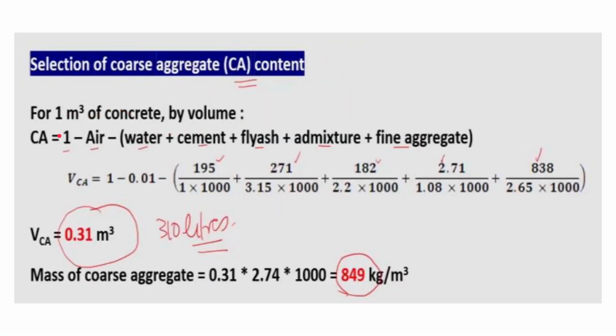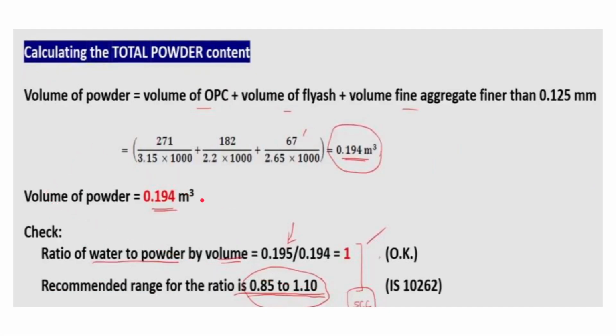Now by using the concept of specific gravity, volume and all, if we equate, we will find the volume of coarse aggregate as 0.31 meter cube. This is the normal calculation procedure, and we have to use this for finding the amount of coarse aggregate to be added. So the mass of coarse aggregate to be added is 0.31 times 2.74 specific gravity into 1000 kg per meter cube, the density of water, which is 849 kg per meter cube. So mass of coarse aggregate has come to be 849, which in normal concrete is generally around 1100 to 1200. So it has reduced.